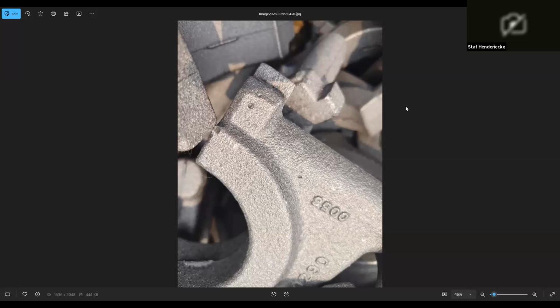And if you say it's at one of its foundries and others maybe not, first look at how well the green sand is rammed. What's the hardness of the green sand? And secondly, don't put a higher carbon equivalent than necessary, because the higher the carbon equivalent you have, the more the expansion will be. And then even sometimes chemically bonded sand cannot withstand it. So it's a matter of comparing the hardness of the sand, the green sand mainly, with the carbon equivalent you're using for these parts.